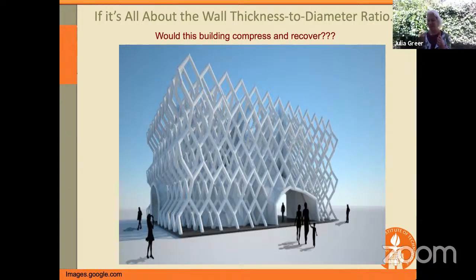And before any of the beam members in a building has a chance to recover, the material will locally fail at one of these flaws, because the probability of finding a flaw or multiple flaws of certain sizes in something that's 10 centimeters thick is 100%. So when we globally apply some kind of compression, the local stresses ahead of these flaws will always exceed the globally applied stress, and certainly the material will shatter and will break before any kind of structural instability takes place, like shell buckling.